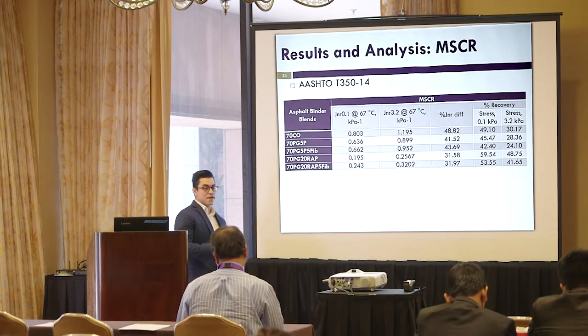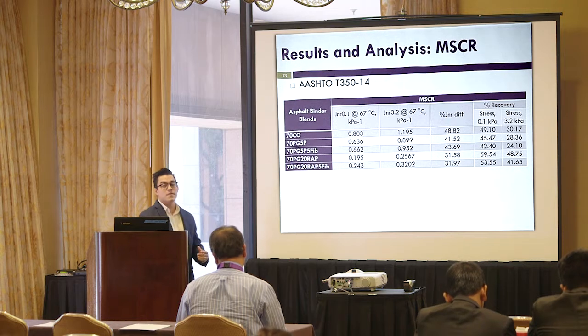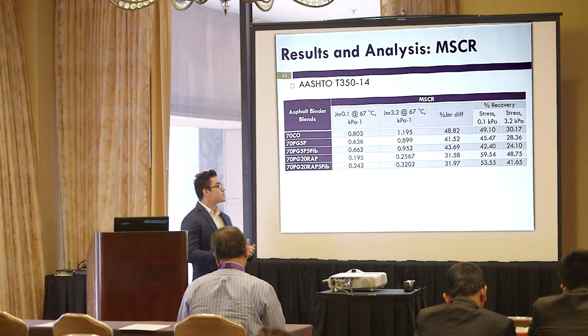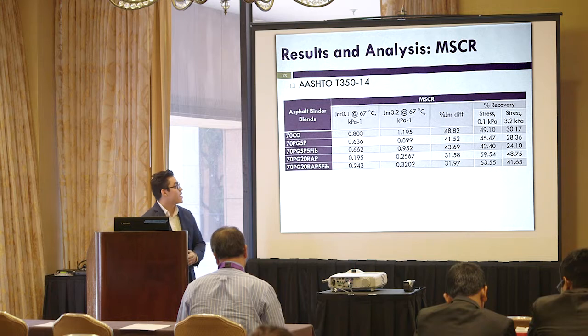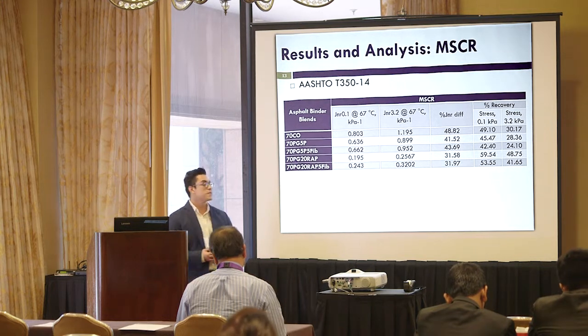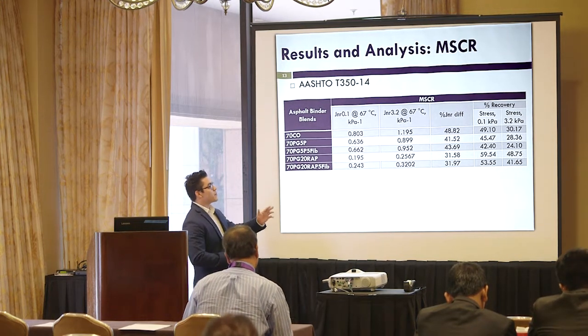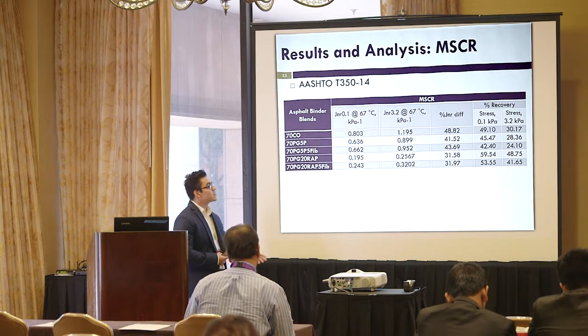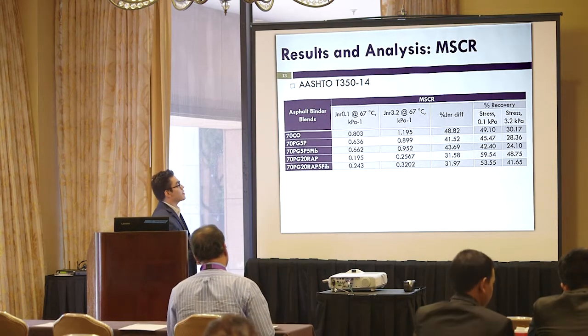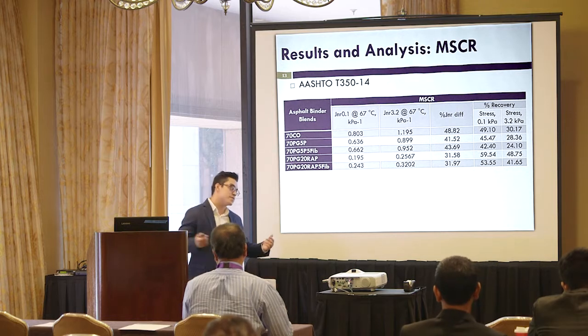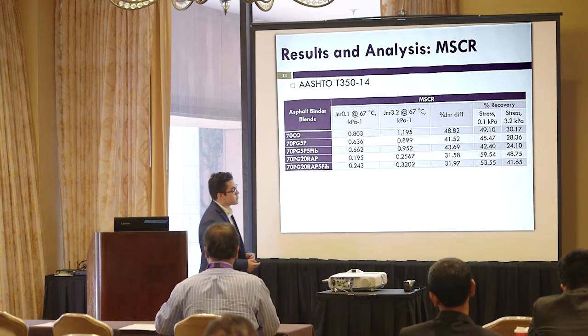For the MSCR test, we observed that the addition of recycled materials and fibers enhanced the performance against permanent deformation, as the non-recoverable creep compliance decreased, and also the percentage recovery increased as we were adding these recycled materials and the fibers.